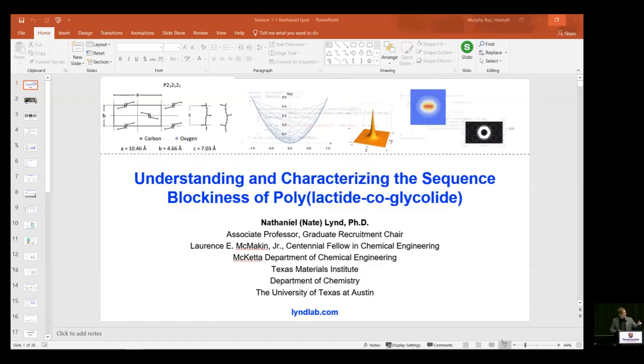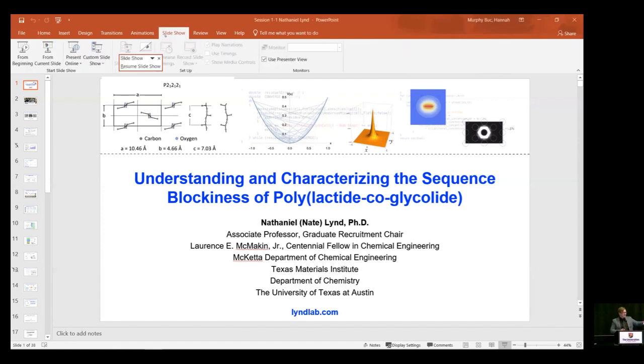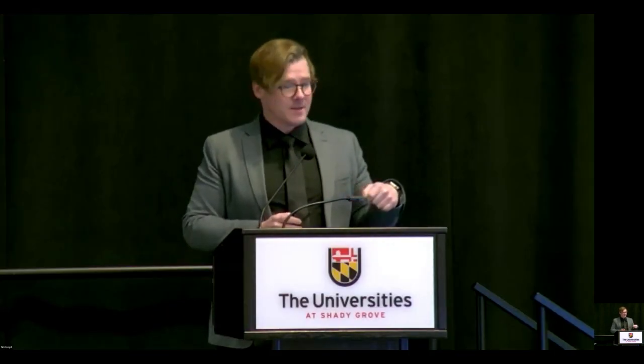But if we look at all of the potential reaction rates that may be occurring in this complex reaction network, we have initiation, polymerization, depolymerization and transesterification. The experiment that we just did said, okay, you can ignore every equation here that has glycolide on the chain end and has glycolide reversing. So we can cross some of these things out.